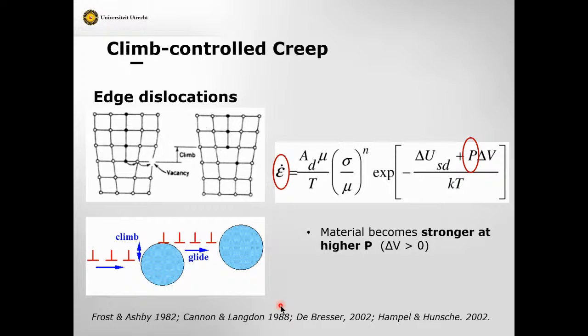We can model this, and it has been done by many, many different authors, as some of them mentioned down here. We can make dislocation scale dynamic models for the motion of dislocations through the crystal lattice and how the rate is controlled by processes such as dislocations climbing over other dislocations which might act as barriers and so on. This is what actually controls the speed of the process. It can be a process called climb, in which dislocations can move up through the lattice, get past obstacles, untangle themselves. The speed of the motion of these dislocations by these different processes controls the creep rate. And you can derive theoretical models for that.